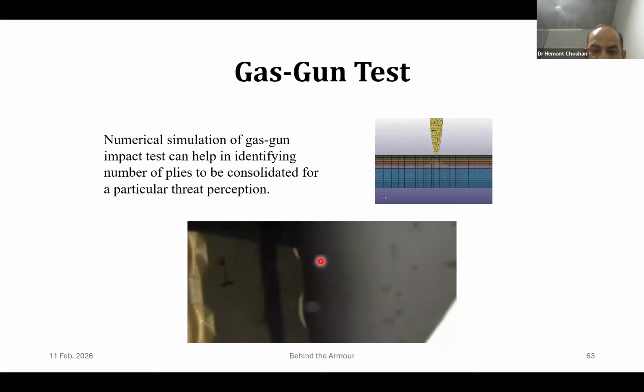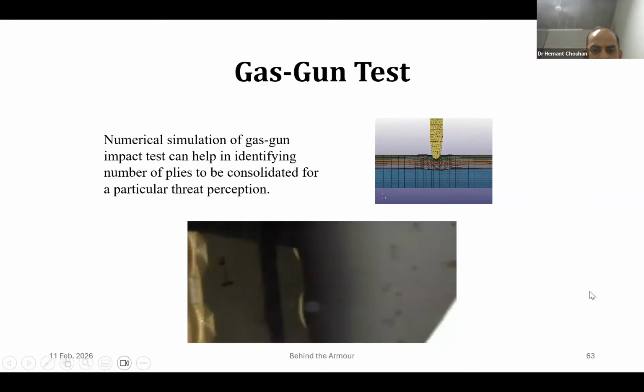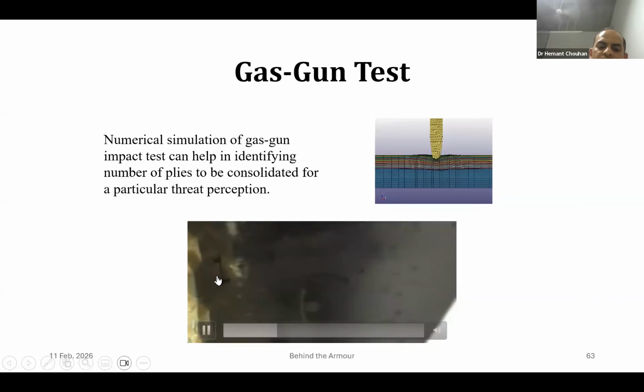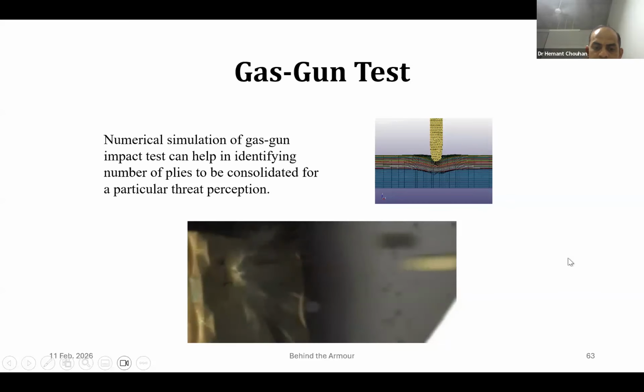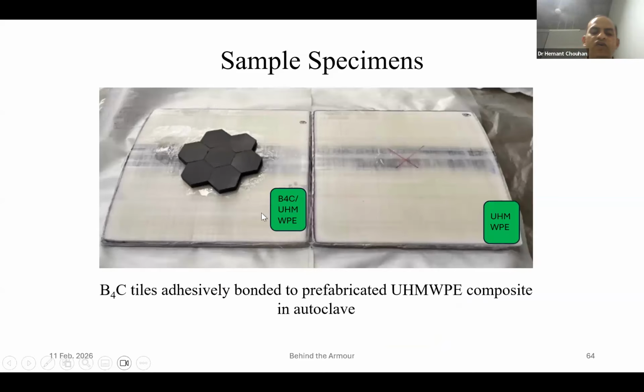So this is the simulation running. And here you can see the bullet of an AK-47 firing upon the panel with a high-speed camera. And this is the debris of the ceramic. These black particles are basically the boron carbide particles. So ultimately what you are producing is a UHMWP backing, and on top of that you are going to have boron carbide, and then wrapped with Kevlar. This is just for your better understanding of how things are.